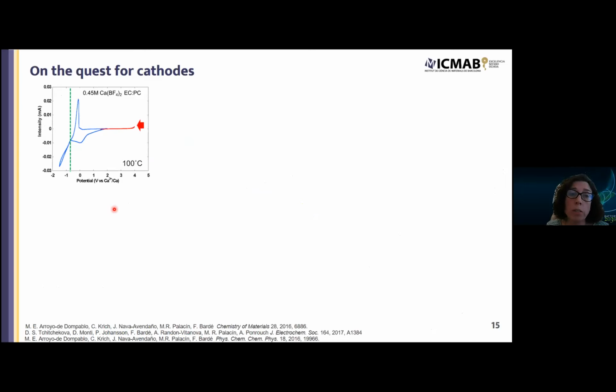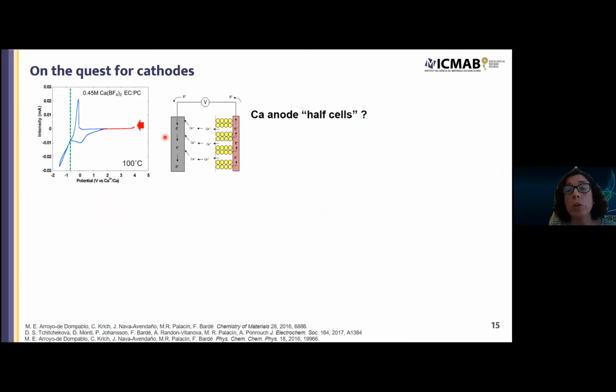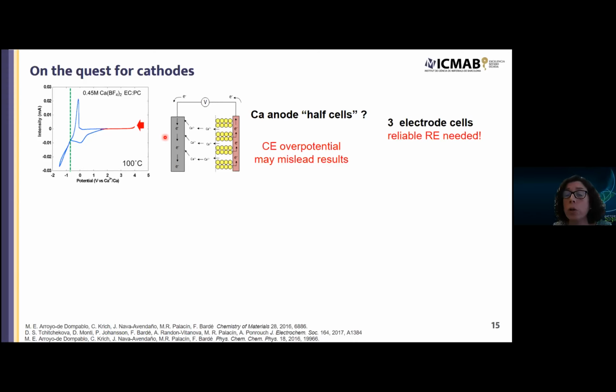So at that point, we started to look for cathodes, and we used the electrolyte with which we had been working, because calcium BF4 is commercial, and also because of the stability at high voltage. And here we were facing a lot of issues with the experimental protocols, because one cannot mimic what is typically done within lithium-ion battery technology, because ideally one would like to assemble half cells with a calcium anode, but I showed you that calcium anodes were very polarized,